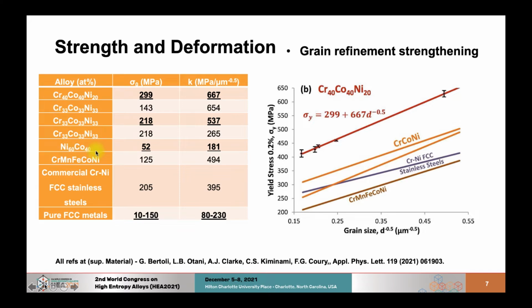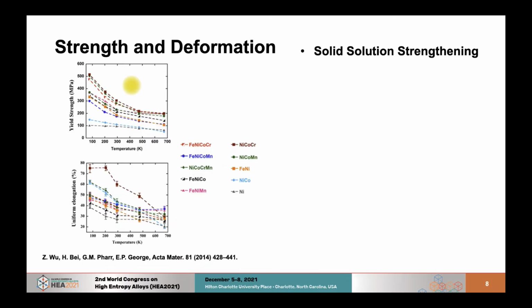So we can see here an alloy without chrome has a very small sigma 0 and a relatively small Hall-Petch grain refinement constant. And when we go to the equiatomic composition, both these constants go up, and then when we go to this alloy that has even higher amounts of chrome, both these constants go up. I'm going to come back to the sigma 0 term soon, but this shows that these chrome cobalt nickel alloys not only are intrinsically strong, but they also can benefit greatly from grain refinement. So studies on techniques and alloying additions to help further increase grain refinement are welcome in this area.